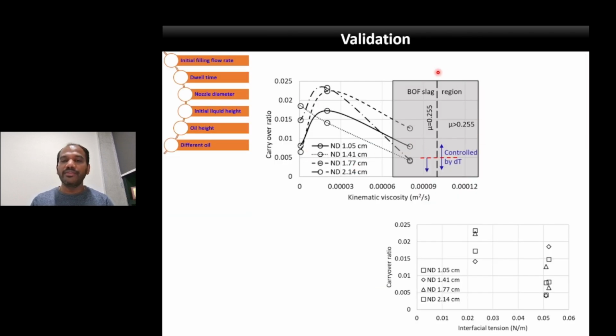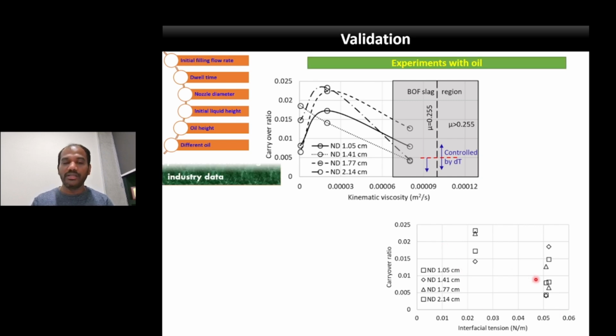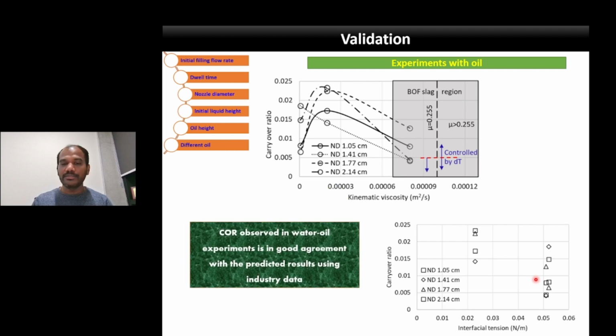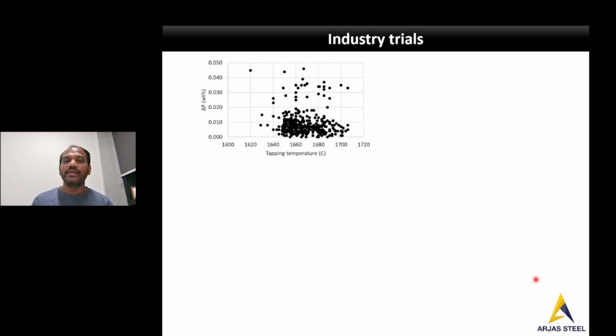You can see that this is the BOF slag regime. The carryover ratio is nothing but kilogram per ton, and this is the BOF regime. And you can see as the kinematic viscosity increases, your slag carryover decreases. And another inference from here, when we plot it with the interfacial tension, it is very clear that as the interfacial tension increases, the slag carryover decreases. These are all very much in agreement with the FactSage results, and we went forward for industry trials to make it.